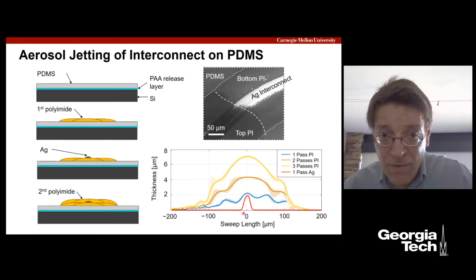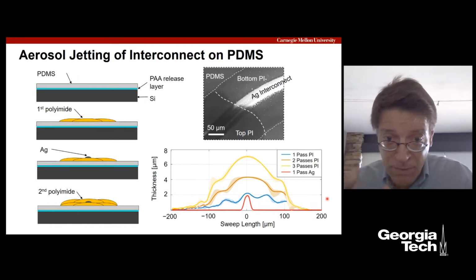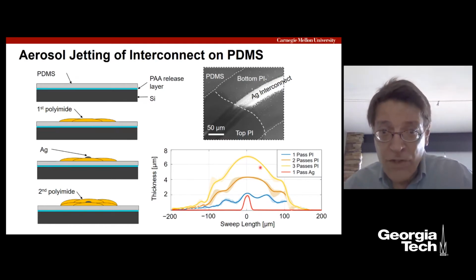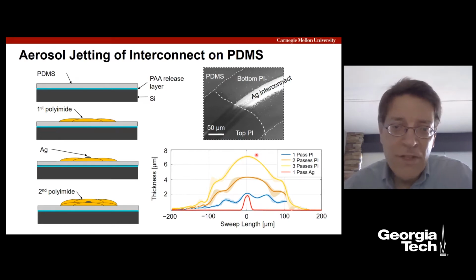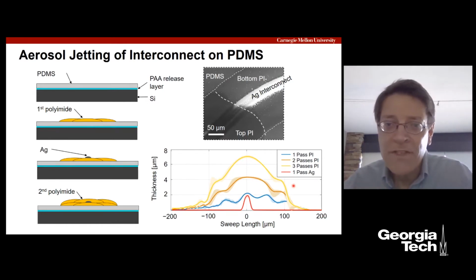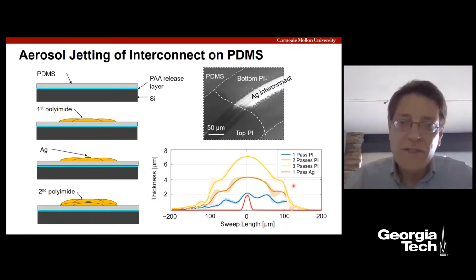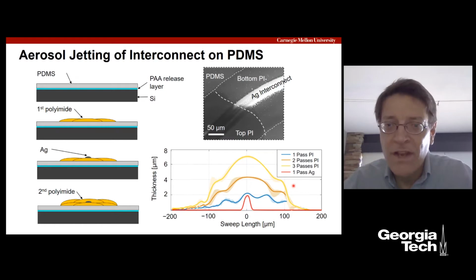This is 1 pass of silver with a narrow nozzle, and then we're using a wider nozzle because we want to coat with the polyimide and also on the bottom. These are just overlaid traces of test structures. So you see the basically linear relationship of passing the 1 layer of polyimide, 2 layers of polyimide, 3 passes of polyimide. And you can see the waviness, and that's because of the passes and choice of overlap as the jet is flowing across. The jet's probably covering on the order of 30 microns per pass. So one has to raster scan that to get enough width.